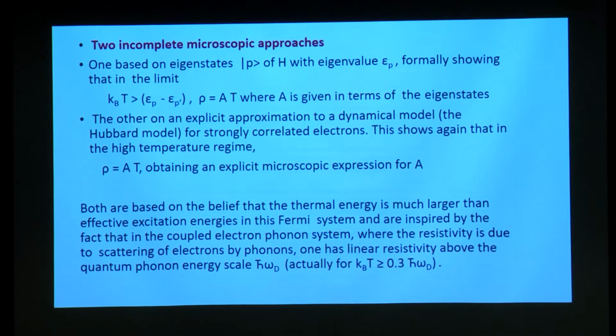Both of these are actually based on the belief that the thermal energy is much larger than the excitation energies in this Fermi system. They are actually inspired by the fact that in pure metals, that is in coupled electron-phonon systems, where the resistivity is due to the scattering of electrons by phonons, one does have linear resistivity above the quantum energy scale. Actually, the phonon quantum energy scale is h omega_D, where omega_D is the Debye frequency. So if the thermal energy is larger than this, they do show linear resistivity. As a matter of fact, they show linear resistivity for somewhat smaller thermal energies.